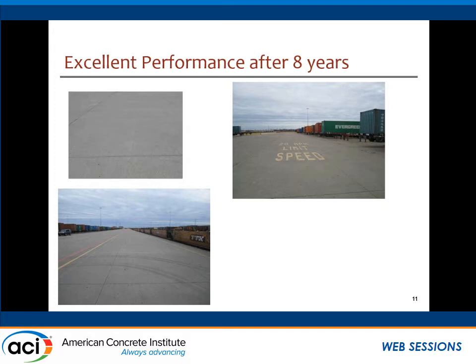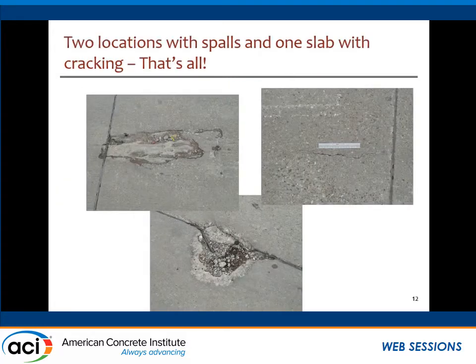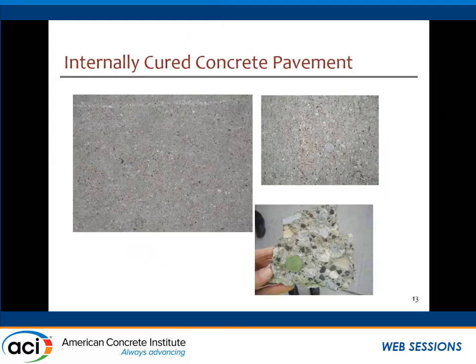We walked the pavement to some extent, and then we were pretty much doing windshield surveys, and the pavement slabs were in great shape. Except we saw 2 locations with some spalling at the joints, and we saw 1 crack. Now that's phenomenal. That's hardly any failures, hardly any distress development over a span of 8 years. And what is it about this pavement? It happens to be an internally cured concrete mix that was used for